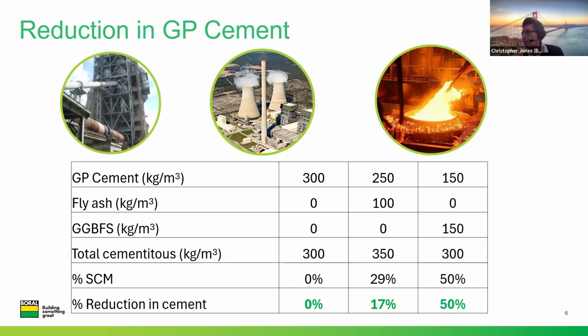When using slag, however, you can replace the cement on a one-for-one basis. So a 30% slag mix is likely to reduce the GP content by 30%. And we can replace much more of the cement with slag than we can with fly ash. The example on the right is a 50% slag mix, which has reduced the GP content by 50%. So the point of these last two slides is to show that to significantly reduce the GP content and the embodied carbon, slag is a much better SCM than fly ash.